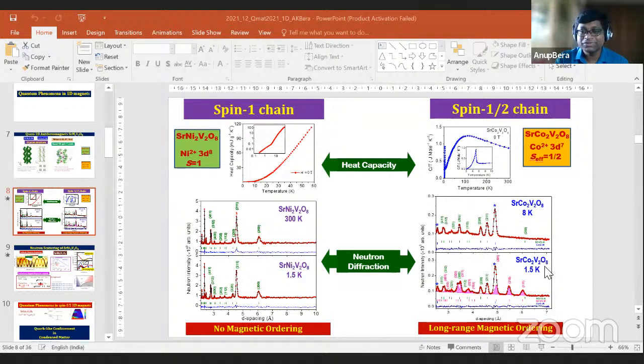If we do this neutron diffraction, I can directly show that there are magnetic Bragg peaks. I have not shown the magnetic structure here. Basically, this is a linear chain, and we are getting the antiparallel alignment of the spins. So it is like a Néel state we are getting. I see. Because of the weak interchain coupling, which is forcing the system to order.